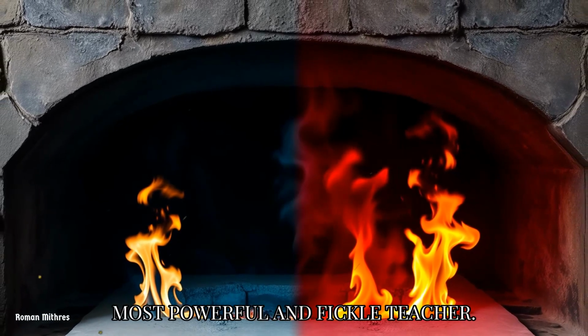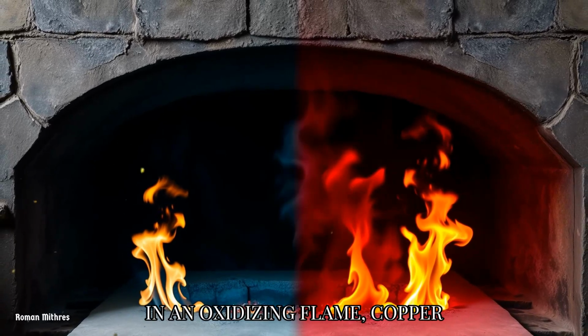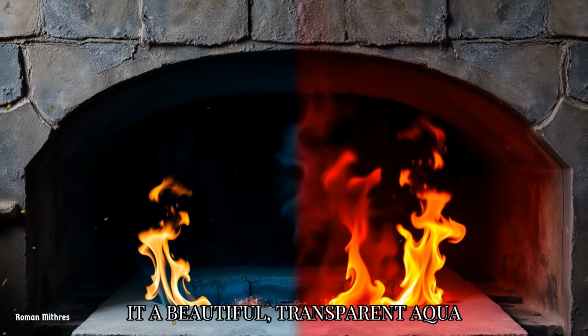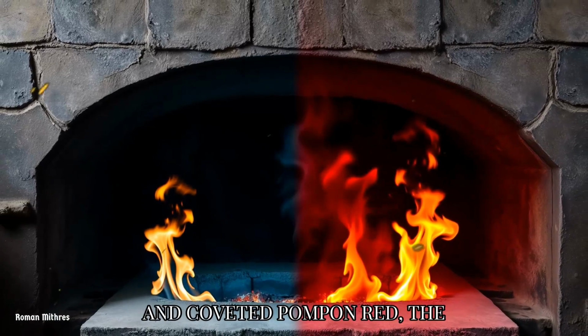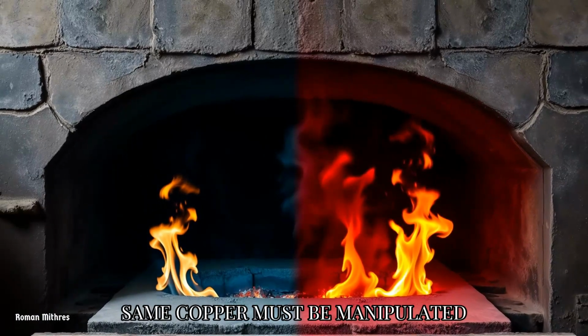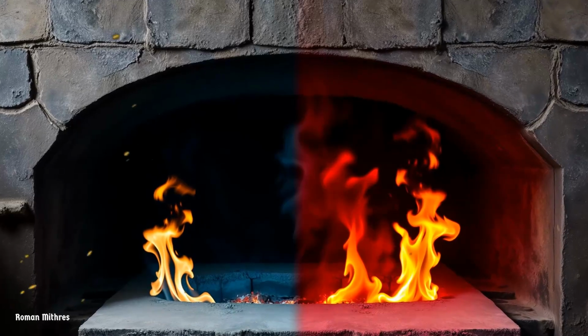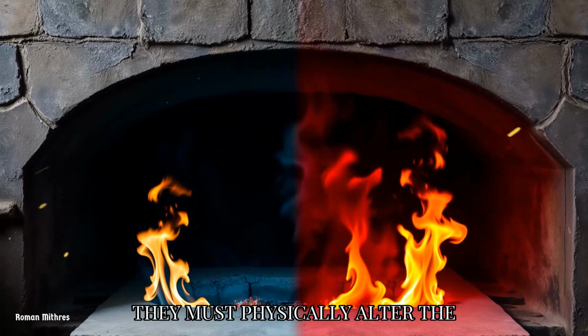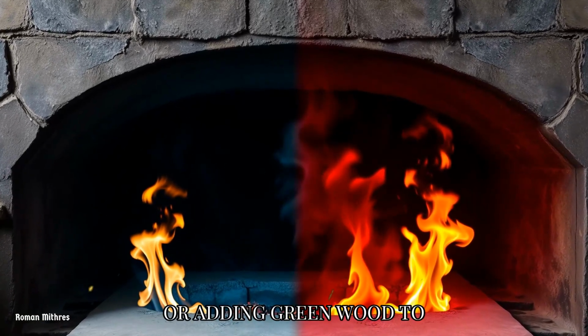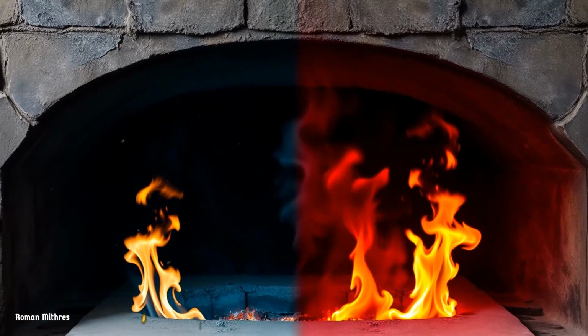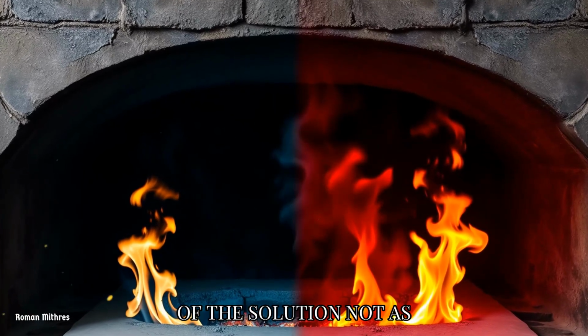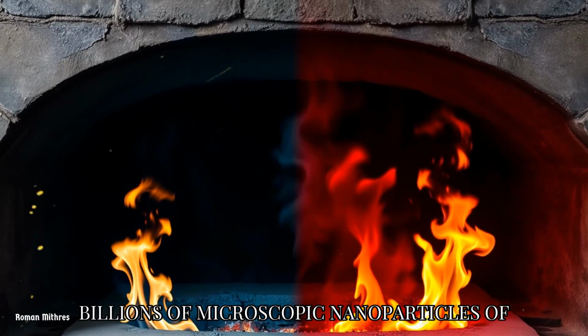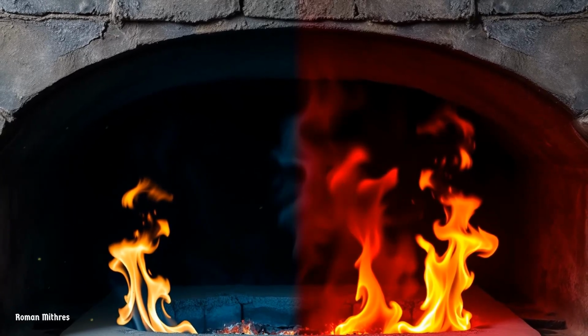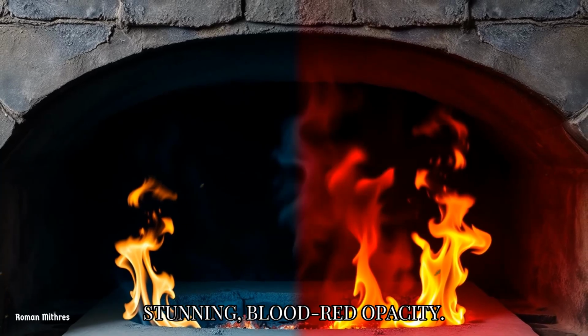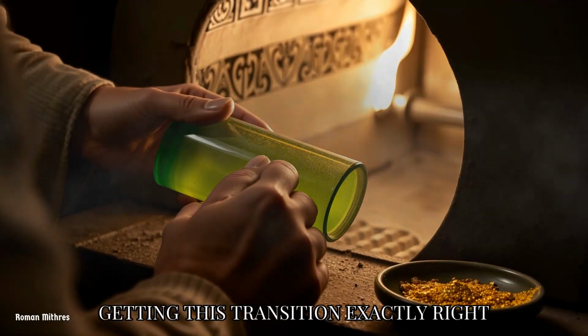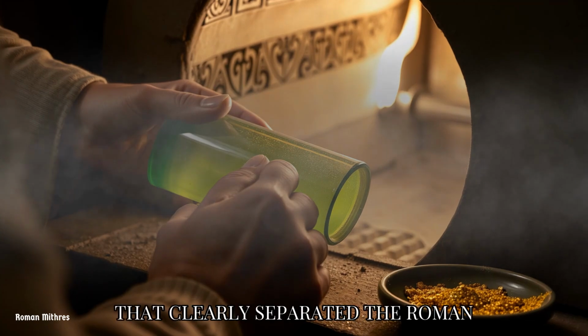The element copper becomes their most powerful and fickle teacher. In an oxidizing flame, copper dissolves into the glass, gifting it a beautiful, transparent aqua blue. But to achieve the legendary and coveted Pompeii red, the same copper must be manipulated in a reducing atmosphere. The modern team learns this through frustrating repetition. They must physically alter the fire itself, partially blocking the air intake or adding green wood to create a smoky, oxygen-poor environment. In these conditions, the copper is forced to precipitate out of the solution not as a dissolved ion, but as billions of microscopic nanoparticles of pure metal suspended in the glass matrix. It is this suspension that scatters the light, creating that stunning blood-red opacity.